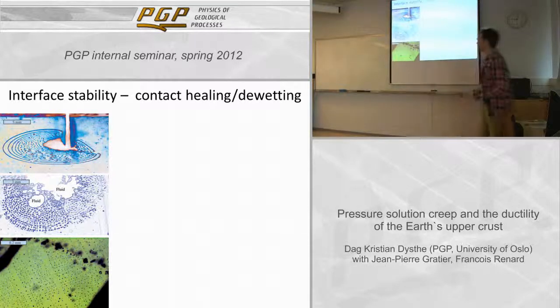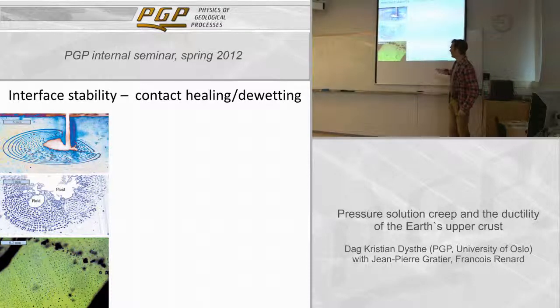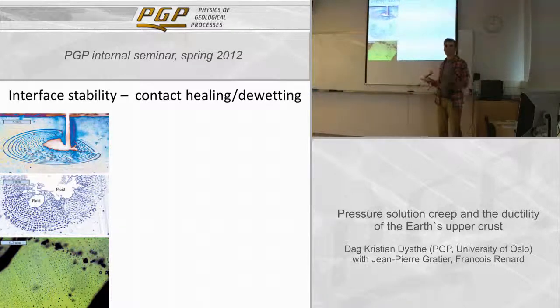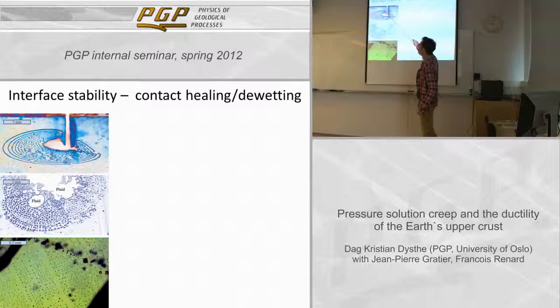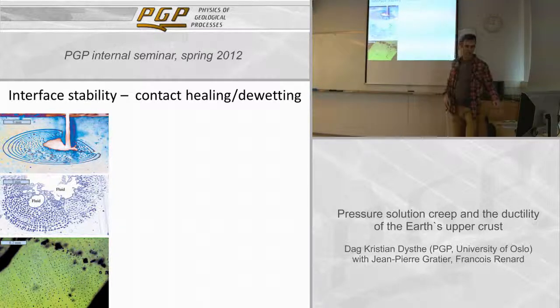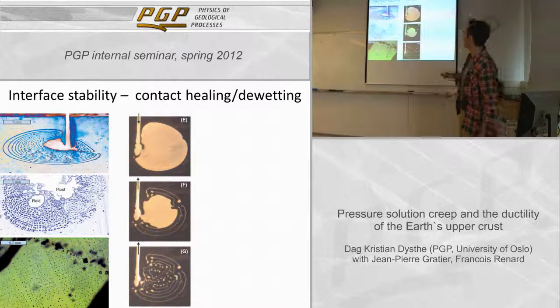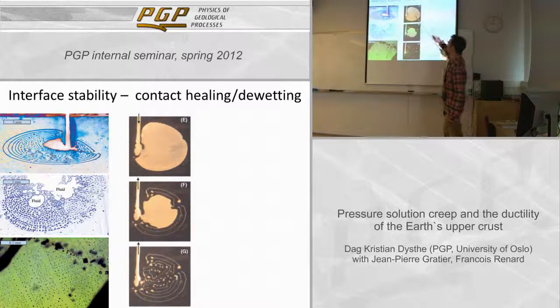And in nature we see lots of former fluid-filled regions that now only have lots of fluid inclusions left on them. They have closed up but have some fluids trapped on them. These are some pictures from experiments that François did here in Oslo quite a few years ago, where we studied the dynamics of this contact healing process, where he filled some cracks in a gel, and just the elastic energy and surface energy started pushing back the oil inside the gel, and pushing it back out of the gel, and what was left was such a network that ended up with lots of small pearls as you find in nature.